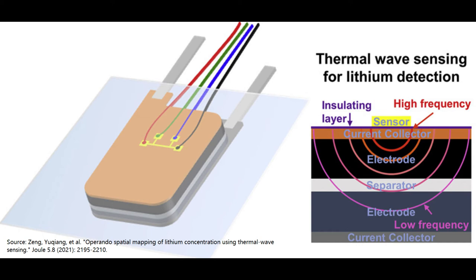And so we found that this let us do operando measurements. So non-invasive measurements on the subsurface properties of the batteries while they are in operation, which allowed us to see some properties and their evolution that previously no one could observe in situ. People had taken batteries and cut them open and taken them apart and measured the individual components, which is very insightful. But you're never really going to get the full picture of how all the components interact with each other during charging and discharging, unless you can do that measurement in a live battery. And that's where I think the big opportunity lay.